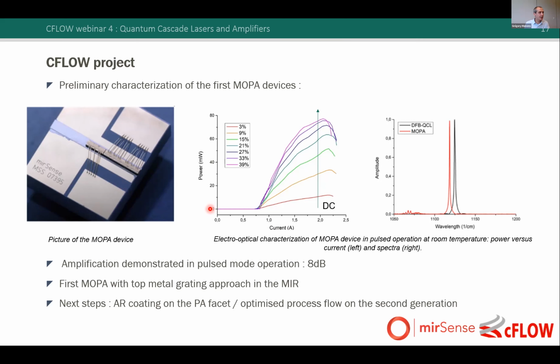So you can see here the evolution of the power versus the current of the MOPA devices at room temperature in pulse mode operation. We used different duty cycles for this pulse mode operation from 3 to 39%, and we achieved an average optical power of 80 milliwatts for this device.